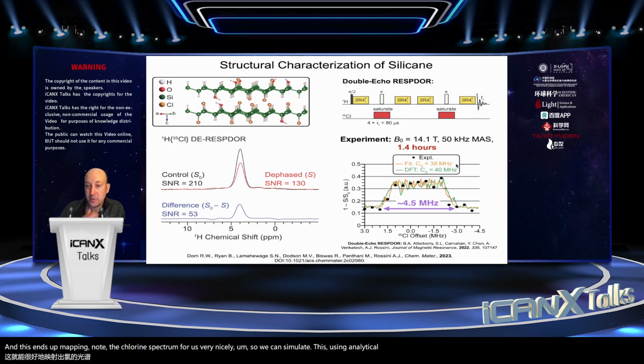Now, how do we get a chlorine spectrum out of this? What we do is we plot this difference signal, or dephasing, as a function of the chlorine pulse offset. And this ends up mapping out the chlorine spectrum for us very nicely. So we can simulate this using a numerical simulation NMR software program called Simpson.